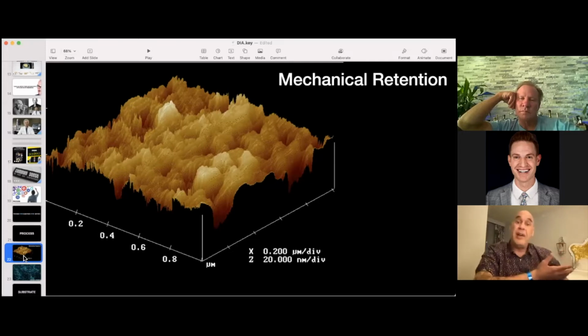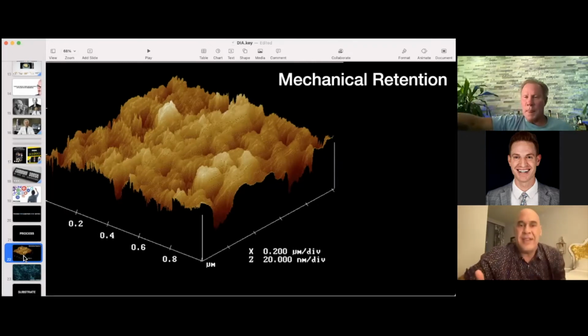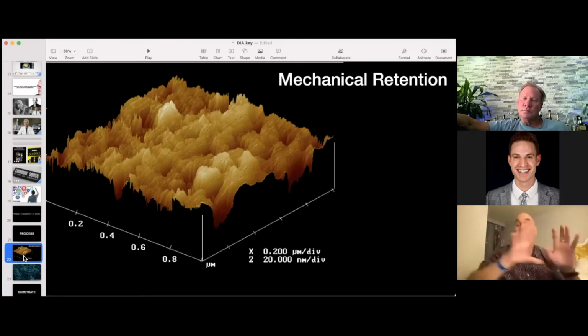Now, if you think about lithium disilicate, oh, I can etch that, but not with phosphoric acid. You need hydrofluoric acid. Why? Because phosphoric acid is not going to cause a dent. It's not going to do anything. It's going to be nothing. You're going to waste your time and you're going to waste your etch. You need hydrofluoric acid, whether it's 5%, 9.5 or 10%, and we will talk about that later on, but you need to etch it.